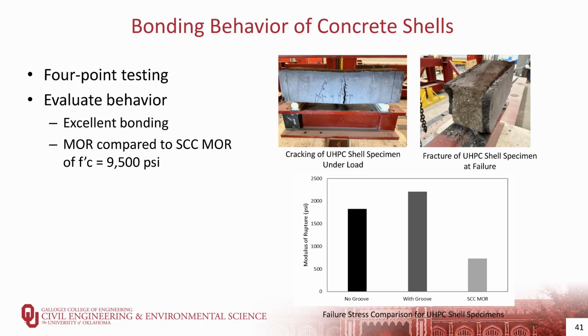Okay. Another question came up on what we are showing. Do these grooves provide composite action, or were they considered for composite action? In terms of what we've done so far, we believe so. The specimens failed due to a single flexural crack propagating all the way through the specimens with no indication of slip between the two. That's where Omar hedged on his conclusion, because we have a limited number of specimens that we've tested, and it is uncertain whether it is going to give us true composite action. Please stay tuned and hopefully we'll have some additional results to present soon.